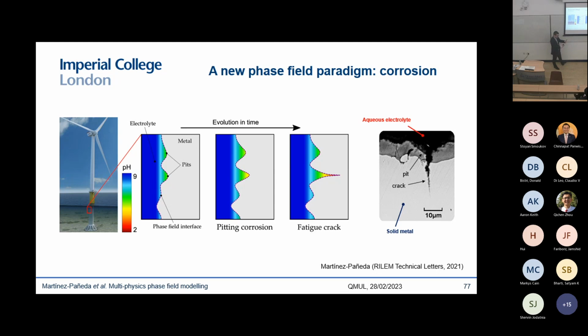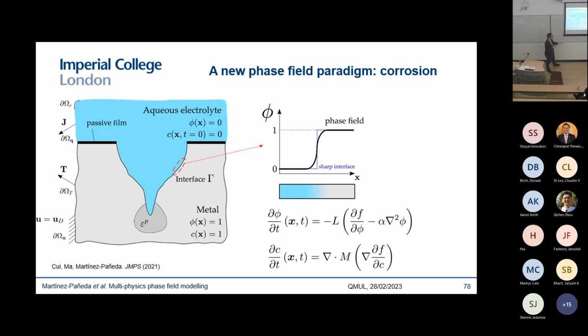If you really want to know how fast that pit is growing, you need to know exactly the morphology of that pit, and then resolve the electrochemistry inside of that pit, the mechanics next to that pit, and the corrosion process. So again, this seems like a very suitable kind of problem for phase field. I'm not going to get into the details for the sake of time, but the idea is that you use the phase field. In this case, the phase field tells you whether you are in the aqueous electrolyte, like seawater, or whether you are in the metal.